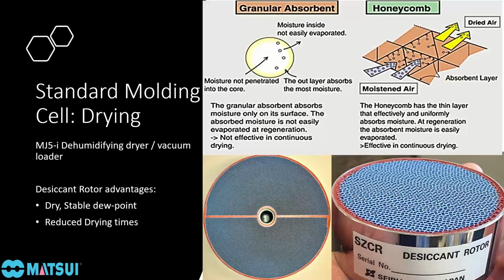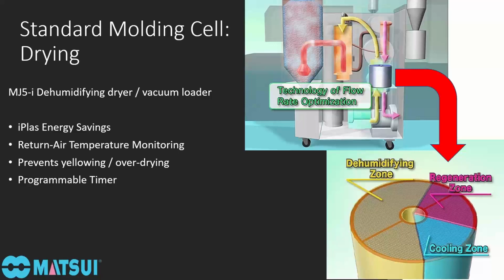We have a higher air to desiccant ratio to pull more moisture out of the airstream, and it's also very easy and energy efficient to purge moisture out of the desiccant. So the combination of the low and stable dew point, along with the higher air to desiccant ratio, allows us to dry materials quicker than desiccant bead type dryers. So we can dry most materials in about 2 to 4 hours.